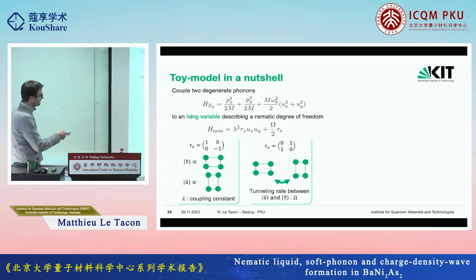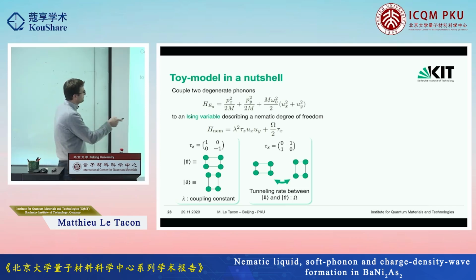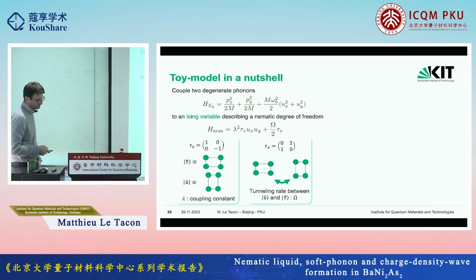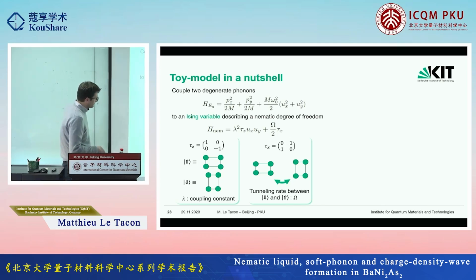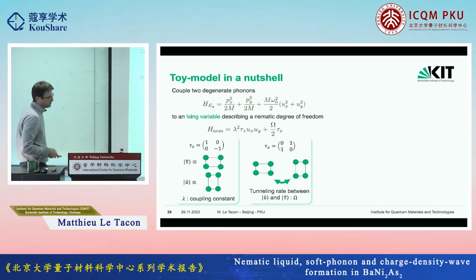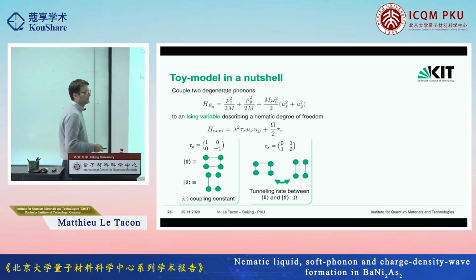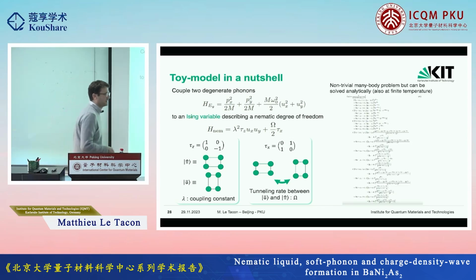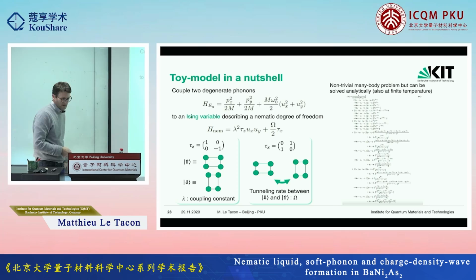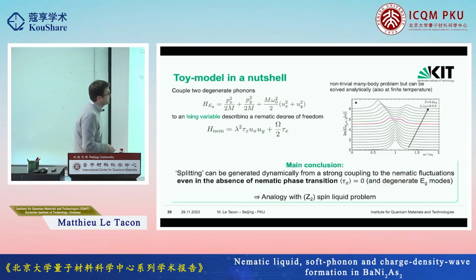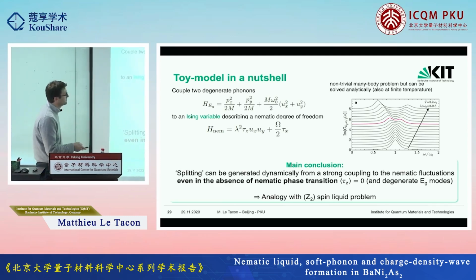And you couple those fluctuations here to your phonon with a coupling constant lambda. So what Jörg liked a lot in that story is that this is a very simple toy model, and it can be solved analytically, and it can be solved analytically also at finite temperature. That doesn't mean it's easy, and it takes Mathematica to work a bit, and that's only one part of the function. So you have these 80-line formulas, and you can solve this at finite temperature. But the result is this, if you compute that. So it's a non-trivial many-body problem, but it can be solved analytically also at finite temperature.